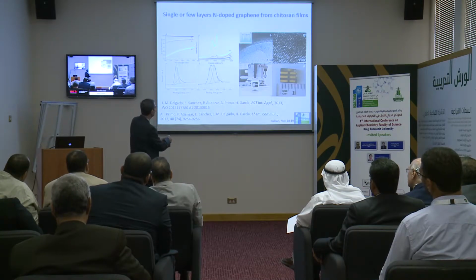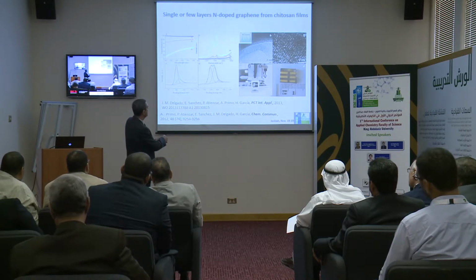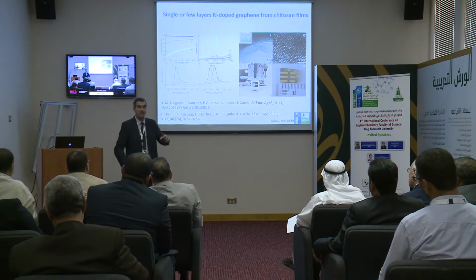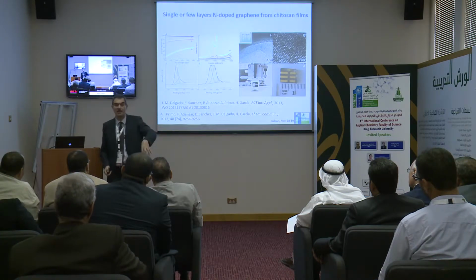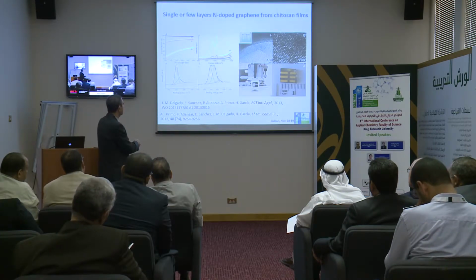So here we have the nitrogen in XPS, and we have 3 populations of nitrogen, 2 major ones. This is the graphitic nitrogen, so just taking away a carbon and putting a nitrogen gives this signal, but we also have another nitrogen that is the pyridinic.